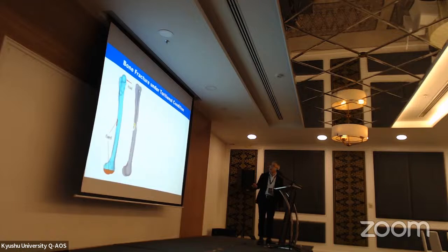Okay, and another interesting result came from this torsional condition. If we apply this kind of torsional condition, then we can see this kind of damage formation very close to the tip of this stem metallic component. This kind of damage and bone fracture is very close to the type B2 fracture, just distal to the stem with stem roots. So that's why, applying this kind of torsional condition, we can get this type B2 bone fracture.